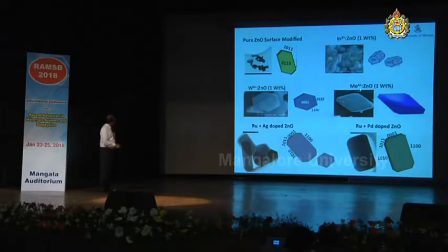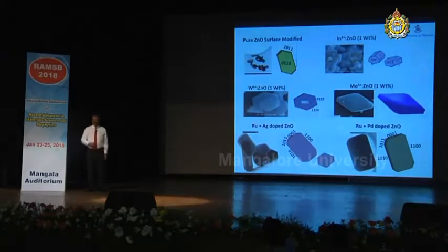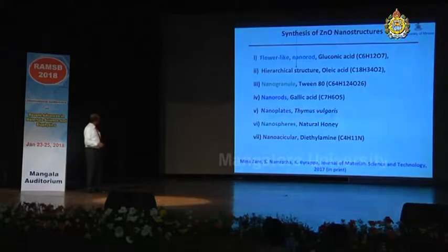And when you have the molybdenum doped, you get a scalenohedral morphology. And we have also doped a couple of dopants like ruthenium and silver. You get this kind of beautiful morphology with reduced aspect ratio even and hexagonal platelets. And you have here the ruthenium and the palladium doped, and the morphology can be tuned this way, and even the size can be controlled this way.